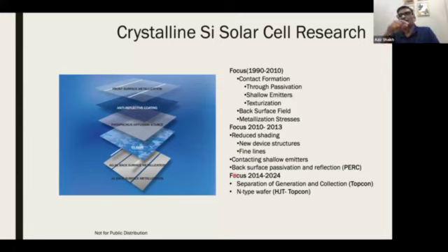Okay, so the carrier N is the dominant carrier. Normally, for this original technology, people were using P type wafer. So if you do P type wafer, then you form N type diffusion on top to make NP junction. So on the N side, you would generate electrons. On the P side, you have holes. So what they do is they put this P plus field, which is called a back surface field, which acts as a reflector if the carriers are going to be lost on the back side. So that acts as a barrier for carriers. They are pushed back towards the junction, and that's the purpose of back surface field.